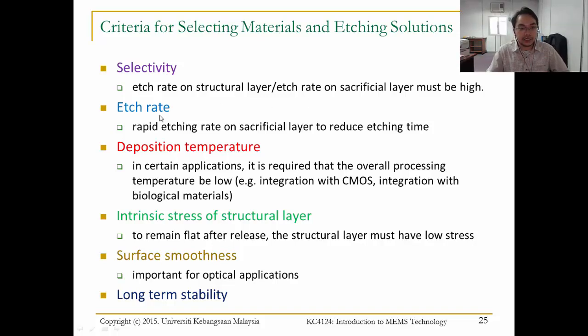Another criterion is the etch rate. Okay, a rapid etching rate on the sacrificial layer to reduce etching time. But sometimes the etch rate has to be low for the structural layer in order to produce a very good and sharp structure. Okay. You should also know the deposition temperature.